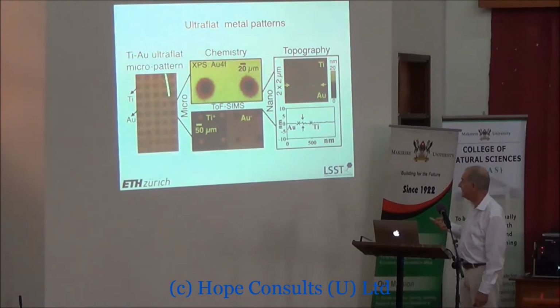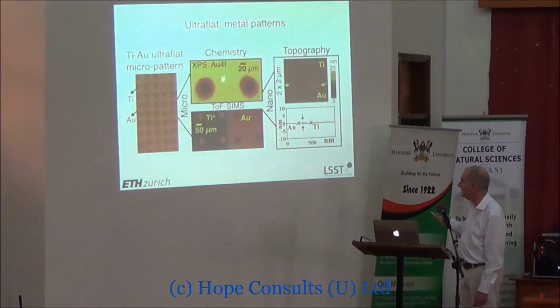This is under a light microscope. Here we've analyzed it with X-ray photoelectron spectroscopy, and you can see the area that is titanium has a very low signal and a very high signal in the gold area, the gold peak. And here we use time of flight secondary ion mass spectrometry to look at the titanium pattern and the gold pattern, and you can see they're complementary because we've got titanium and gold.